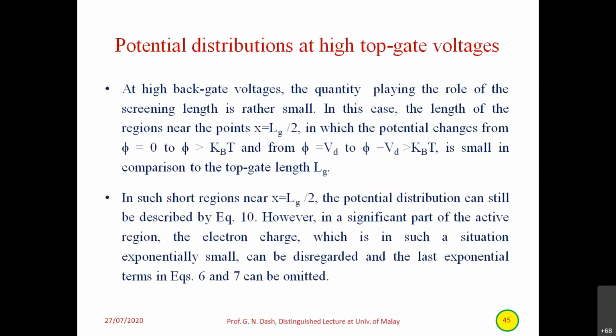Now, potential distribution at high back gate voltage, the quantity playing the role of the screening length is rather small. In this case, the length of the region near this, L_G by 2, in which the potential changes from phi equal to 0 to phi greater than K_B T, and from phi equal to V_d to phi equal to phi minus V_d greater than K_B T, is small in comparison to the top gate length. In such short regions near the middle, the potential distribution can still be described by equation 10.